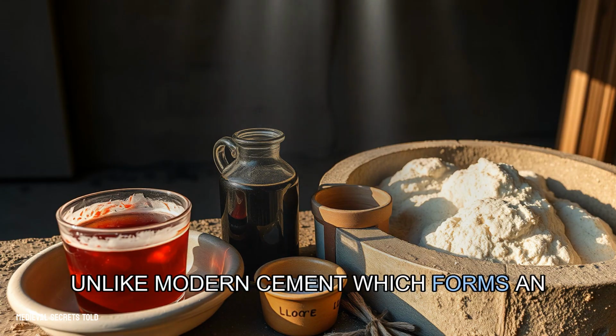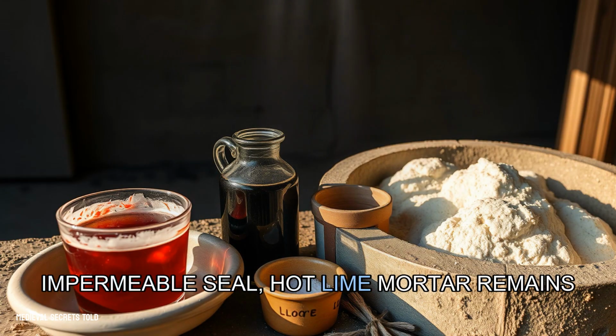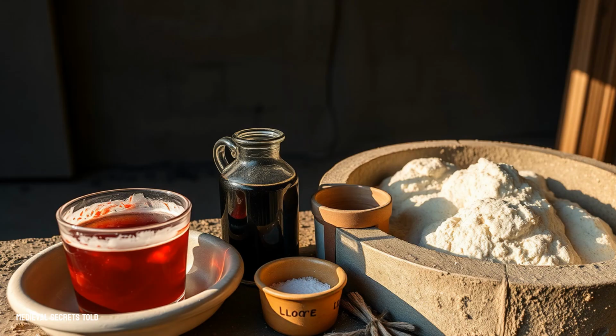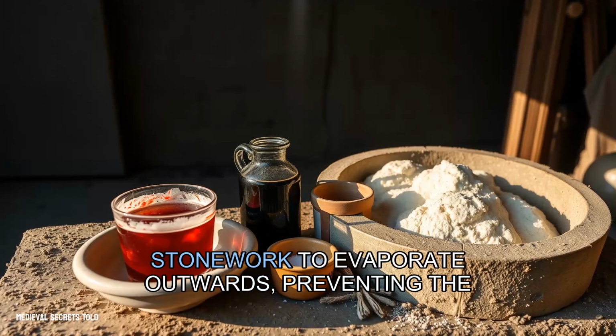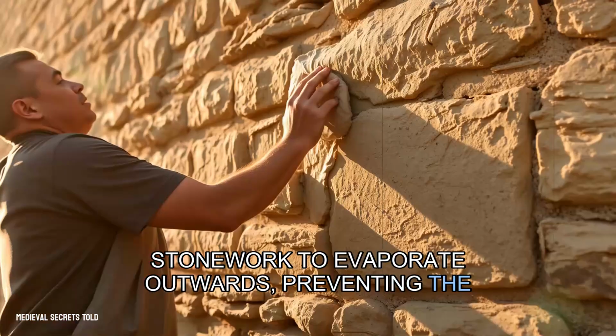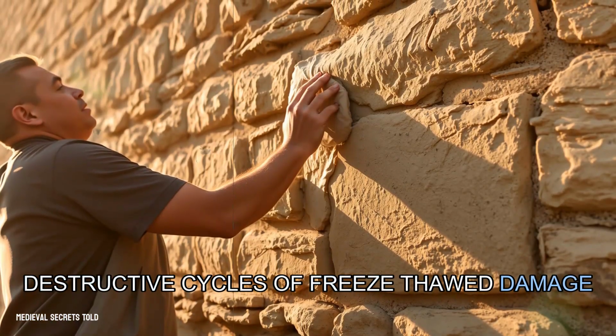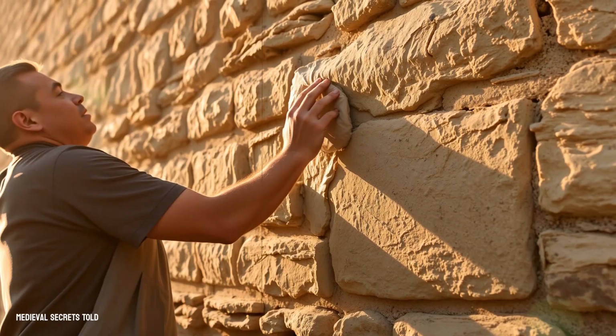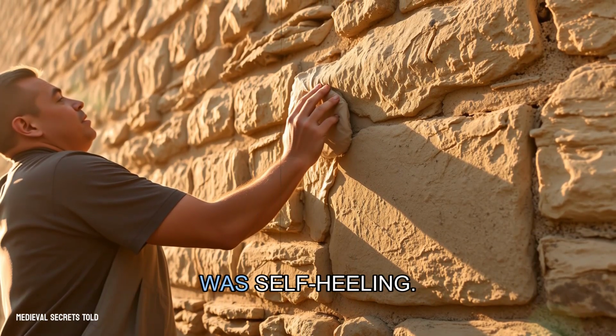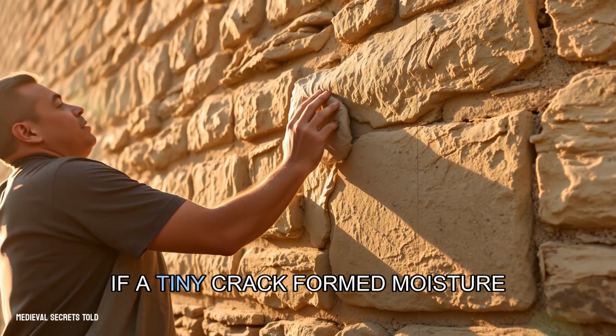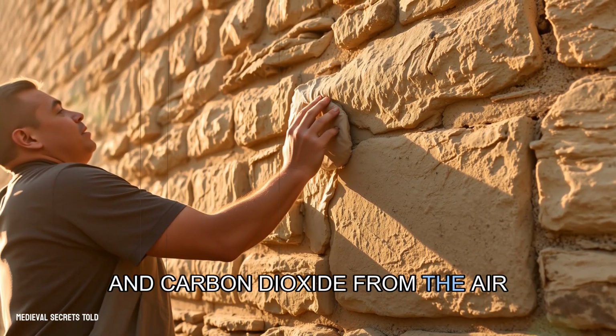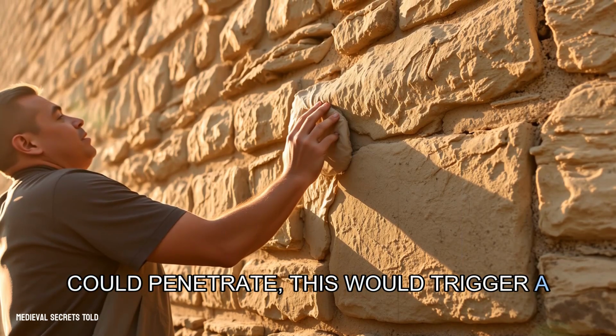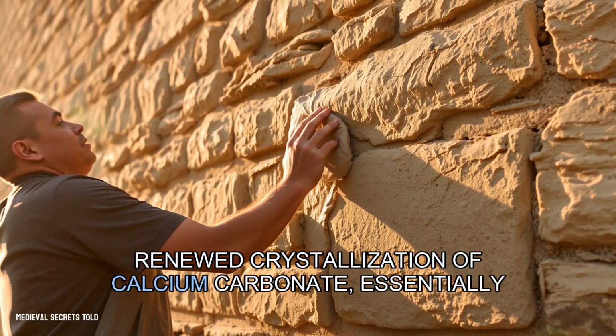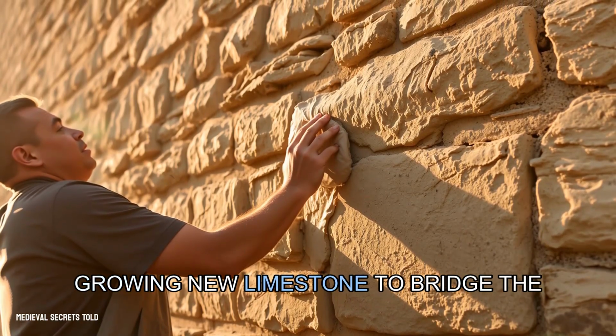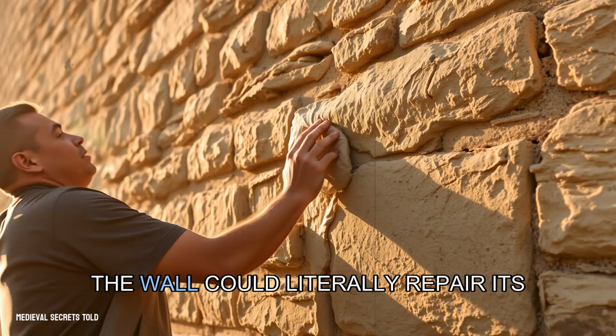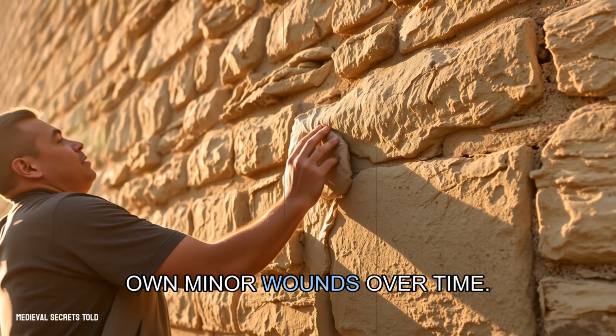Unlike modern cement, which forms an impermeable seal, hot lime mortar remains slightly porous. This allows moisture trapped within the stonework to evaporate outwards, preventing the destructive cycles of freeze-thaw damage that can shatter stone from within. Second, and perhaps more remarkably, it was self-healing. If a tiny crack formed, moisture and carbon dioxide from the air could penetrate. This would trigger a renewed crystallization of calcium carbonate, essentially growing new limestone to bridge the gap. The wall could literally repair its own minor wounds over time.